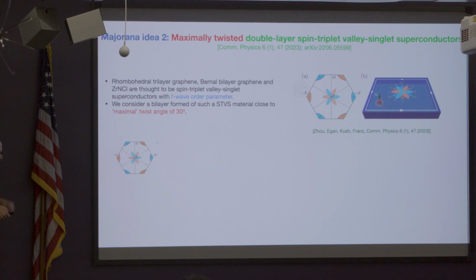So let me show you a quick animation how this could work. So I take one layer of this material. I take another layer. Now I rotate it by 30 degrees, and I make it into a bilayer. Okay? Now, notice what's happening here. What's happening here is that the 2 order parameters, which now sort of cover this whole new Fermi surface, are being frustrated, right? Because blue, wherever blue is touching orange, that's where the order parameter is unhappy, because there's positive trying to connect with the negative. Okay? And that already tells you that's somewhat similar to when you have 2 D-wave order parameters with 45-degree twist, there is a similar frustration.